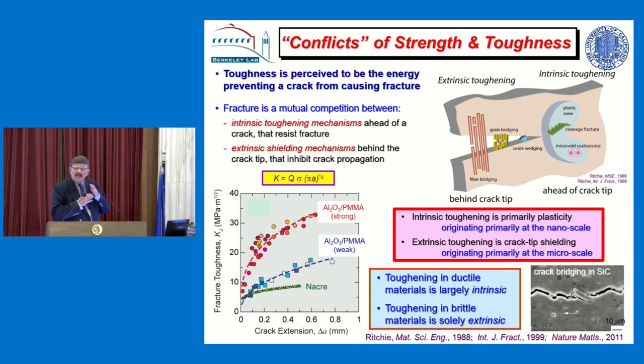Could be dislocations piling up against a particle and breaking the particle. It could be voids forming around precipitates or something like that. That is essentially intrinsic toughness. Most ductile materials, metals, are toughened this way. It takes place ahead of the crack tip, as I said before, and the length scales are typically of the order of nanometers. We're talking about dislocations, Burgers vectors, and that kind of thing.